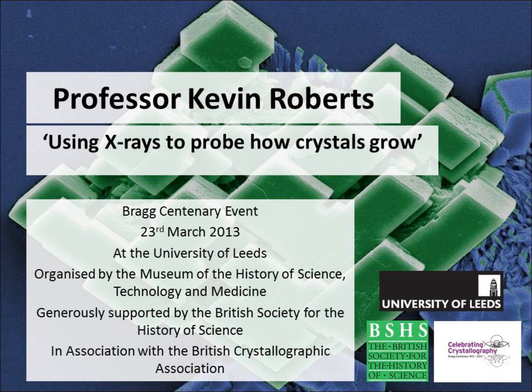I'm just going to run you through a gallery of pictures I've taken over the years. I think a lot of them are not published, but I just fished them out of my album. And this is a material called lithium hydrogen ammonium sulfate. This is a Bragg diffraction image of the crystal. I take the crystal, a big crystal, and I scan it across the X-ray beam, using the so-called technique of X-ray topography, and it just shows lots of pretty things. These are the dislocations, these lovely little lines. This is a dislocation when it moves.